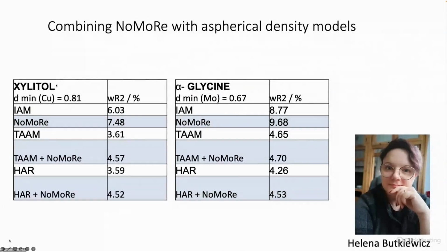She has already done it for xylitol and alpha-glycine, and what we can see is that in general, for the normal mode refinement combined with the TAAM model, the transferable aspherical atom model, we are approaching the results where we use the standard anisotropic displacement parameters. So we are getting there, but the densities are still slightly higher. The R factors are still slightly higher. This may be okay because our model is perhaps more physically meaningful than the standard anisotropic displacement parameters that we use.